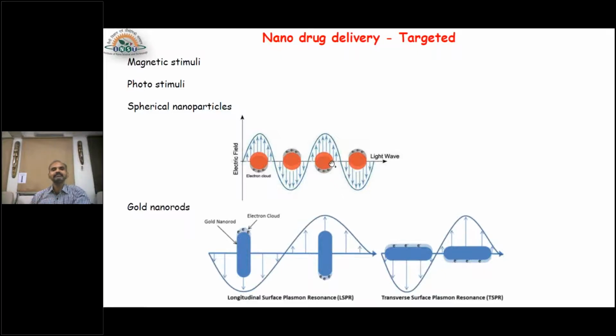That is the phenomenon that is studied with the increase of particle size, and scientists used it to prepare a gold nanorod. In the gold nanorod, you are not increasing the size totally, so you are not blocking the vessels. You are increasing the size in one axis. Then the plasmons are wide apart, and the oscillation is slower, and when the oscillation is slower, you get an NIR absorbance. This is the longitudinal oscillation, and this is the transverse oscillation. This transverse oscillation gives the same 520 nanometer absorbance.